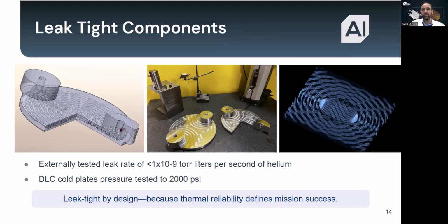On the defense side, we've pressure tested our direct liquid cooling plates to 2000 psi. It's an order of magnitude higher than typical operating pressures in most platforms, giving system designers enormous confidence and margin in their products. This performance is enabled by our stack forging process because we fabricate a single-piece monolithic structure with no brazing, seals, or O-rings. And there simply aren't the traditional failure points that we see in other processing methods. So whether in a semiconductor fab that demands absolute reliability or in defense platforms under combat stress, Alloy components are not just high performance, they're rugged, leak-free, and designed for mission assurance.